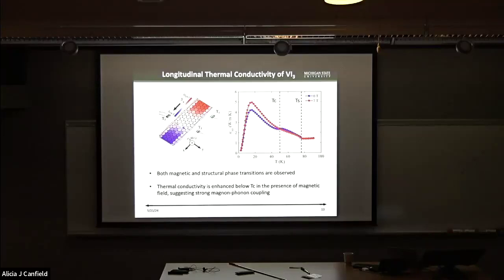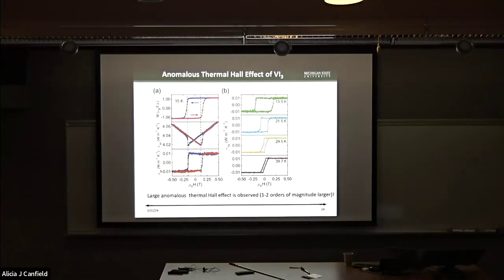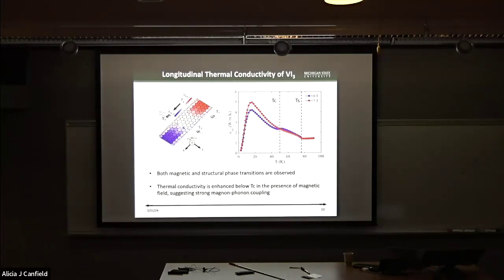Then when we apply a 7 Tesla magnetic field, we are going to push up the magnon band, and as a result, the magnon population is going to reduce. And this is going to lead to the reduction of the phonon scattering by the magnons. This is going to at least partially restore the phonon contribution to the total thermal conductivity. And again, this is exactly what we observed, right? In the presence of the magnetic field, the thermal conductivity is enhanced. So just to come back to my question, this is reproduced also from sample to sample.